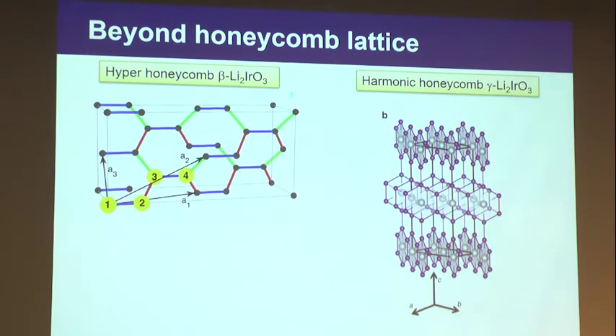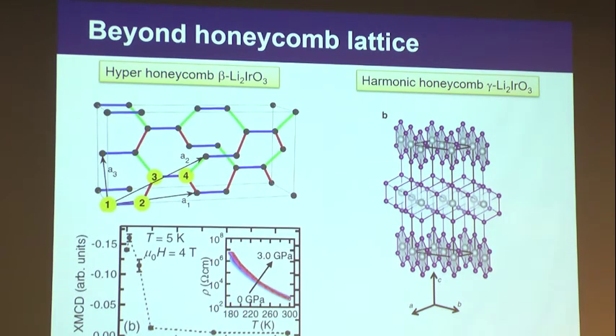Beta phase of lithium iridium oxide, where it's essentially a honeycomb lattice, but in a convoluted three-dimensional way. And there's another, gamma phase of lithium iridium oxide synthesized by James Analytis's group at Berkeley, where you can see that there's a honeycomb lattice, but the next honeycomb is twisted, and so on. So that's kind of like a honeycomb lattice, but slightly different. But in both cases, magnetic ordering sets in, so therefore they are not quantum spin liquids.